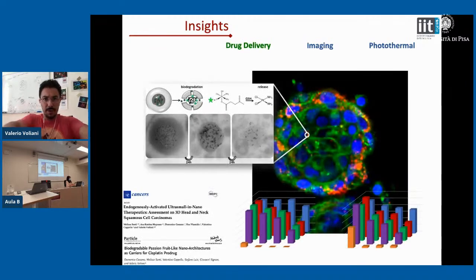Now, very briefly, because I think I'm almost finished with my time, some insights about the passion-fruit-like nanoarchitectures. So we employed our platforms for drug delivery. We inserted a cis-platinum prodrug, an octahedral complex that is released only inside cells thanks to the glutathione concentration in cells. So we have developed a double-controlled releasing system. The double control results from the degradation of the shell and then the interaction with the glutathione. So cis-platinum is released only in the target.